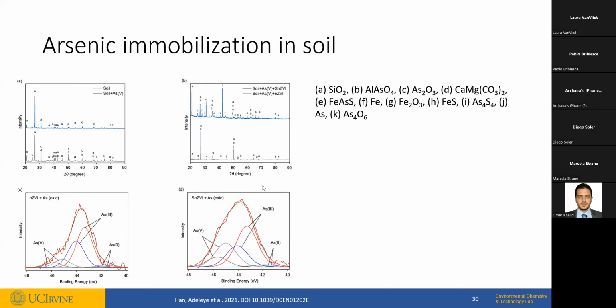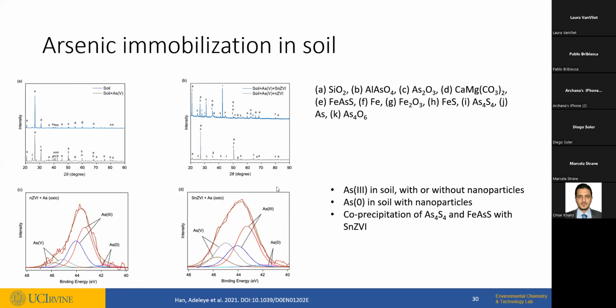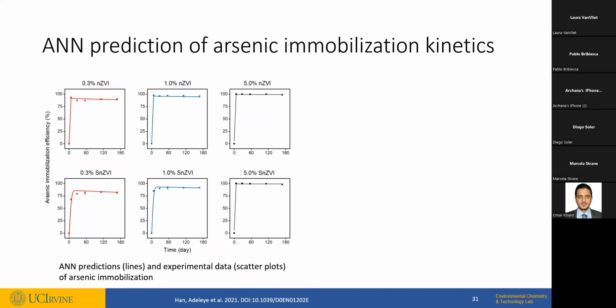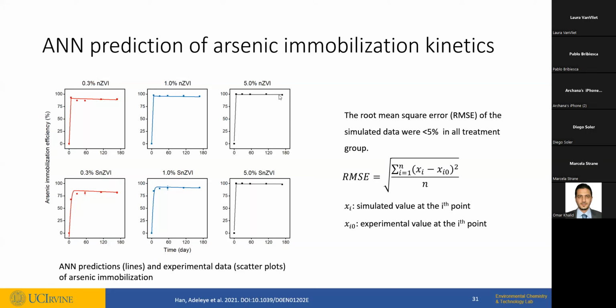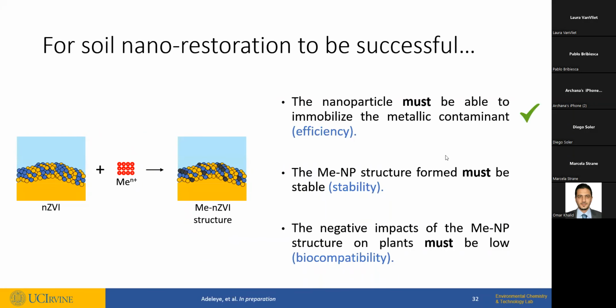We also dug deep into the mechanism of arsenic immobilization. And what we found was, well, arsenic was being reduced from 5 to 3 and 0. And arsenic was co-precipitating with some of the sulfide species in SNZVI. In addition, we saw evidence of arsenic adsorption to the surface of the nanoparticle based on the arsenic 5 peak in the XPS. And just real quick, just wanted to say we did use ANN to also model the kinetics of arsenic removal. And you can see clearly here that the model, which is the lines, compared pretty well to experimental data, which are the dots, and the root mean square error was less than 5% in all the cases. So we checked the first box.